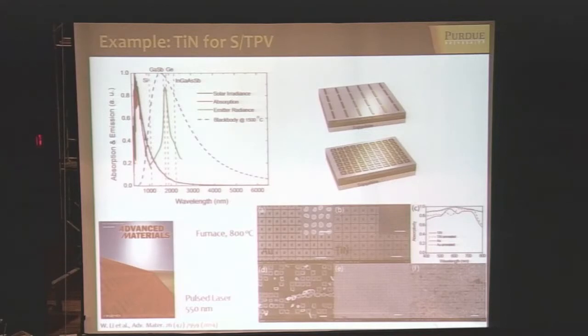And to prove that you could indeed heat it up to the needed temperatures—by the way, the whole structure could be just 100 nanometers in thickness. It's much simpler than what you could use with, for example, photonic crystals, yet another alternative approach.